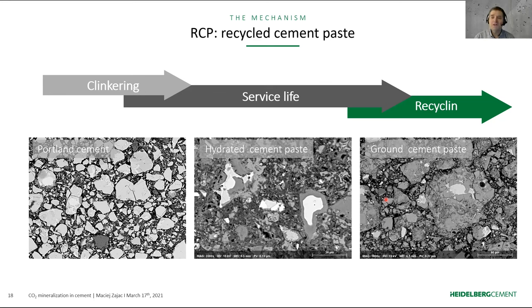To answer the second question, we have done a bigger study on the quality of the paste. For example, we made synthetic materials based on CEM I, so neat Portland cement containing 70% Portland clinker, and slag cement containing 50% slag and more. And we have compared the carbonation characteristics of such materials and later their performance in cement. There are differences, but I would rather call them not so important.